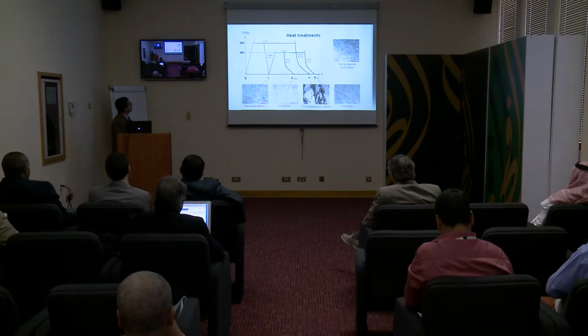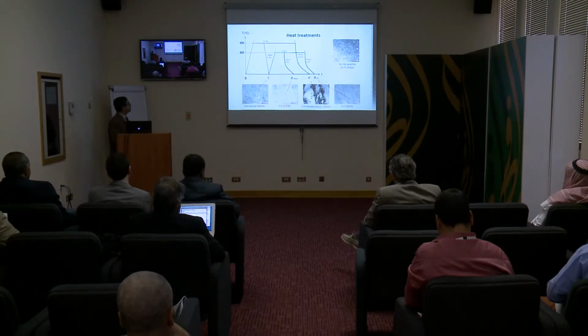And the last two are a tempering of martensite, and then an annealing during two different times, leading to this and this microstructure, which are more homogeneous and have almost the same hardness as the as received one.